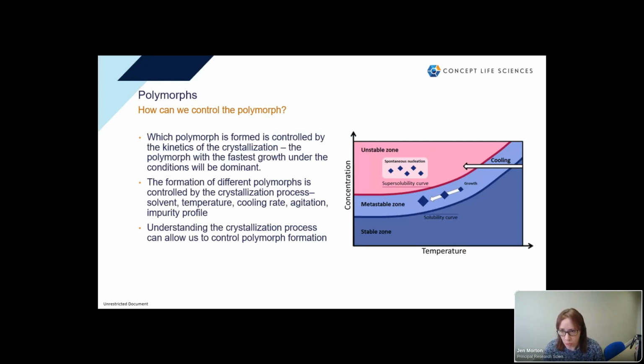So how can we control the polymorph? Very often, the final stage of a drug substance synthesis will be a recrystallization, and a recrystallization gives us an opportunity to control the polymorph. This diagram shows how the condition of a solution changes with temperature and concentration. In the stable zone, we have enough solvent to fully solubilize the material. The material's happy in solution, and there's no need for any precipitation. In the pink zone, the unstable zone, where the concentration is higher, there's not enough solvent there to keep the material fully dissolved. And that means that the material can start to spontaneously precipitate. For chemists, that's crashing out.